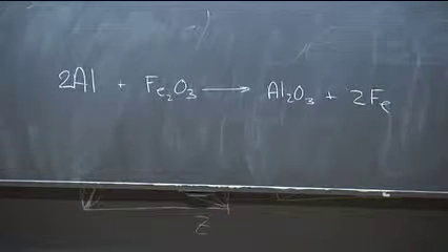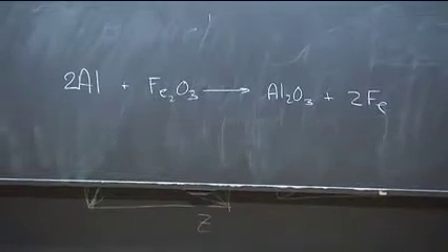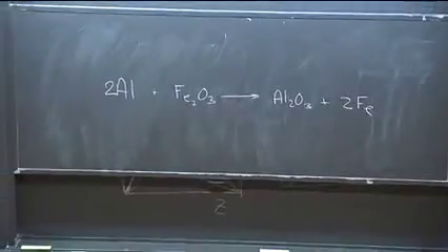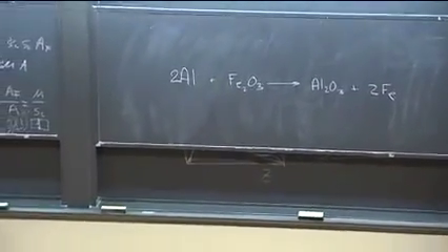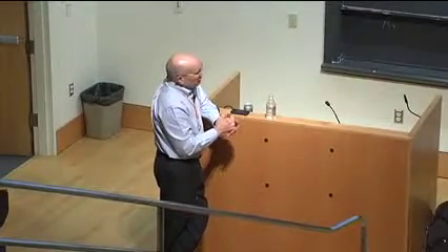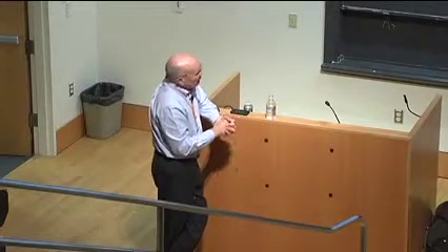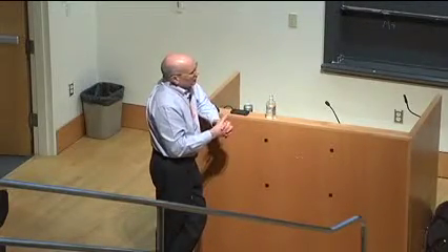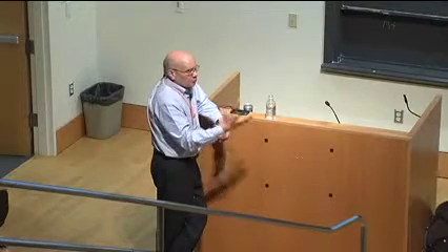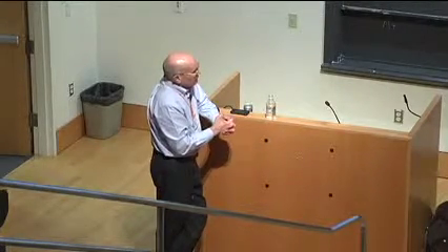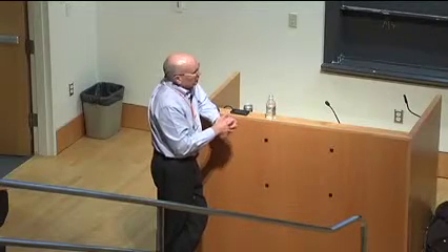So say, for example, I had readily available aluminum and iron oxide, and I'm just showing this because it's a classical thermite reaction. But suppose I had those materials readily available, and I wanted to either make the aluminum oxide or the iron itself because it was much rarer or more expensive. This would show, if indeed this reaction was exothermic, I could actually use the exothermicity from the reaction to actually make this material. And this is really the area of using combustion to make materials. It's really been referred to as SHS, self-propagating high-temperature synthesis of materials.